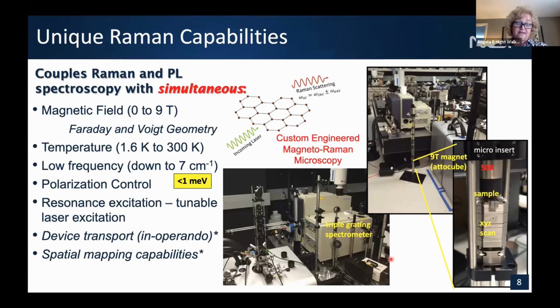The other unique thing that we bring to this discussion is resonance excitation. So with Raman, as you know, it's kind of a weak process. So if it's possible to enhance the Raman scatter through matching and absorption, that would be very desirable. Well, unless you burn the sample. But we do have many laser lines. We have tunable sources that really span the entire visible, from the 400s to nearly 900 nanometers in excitation.